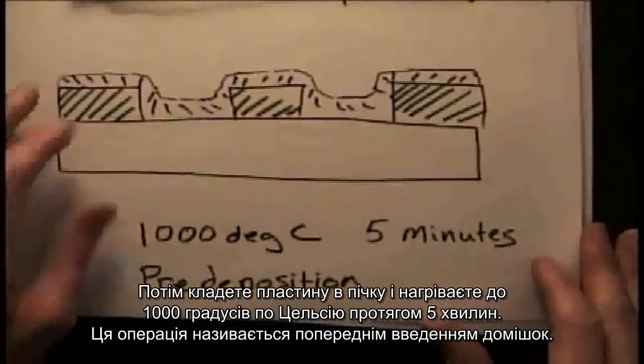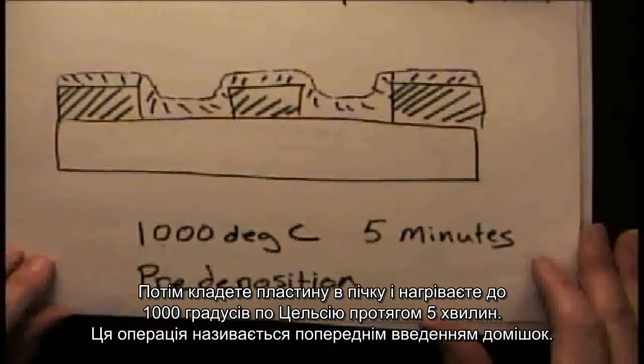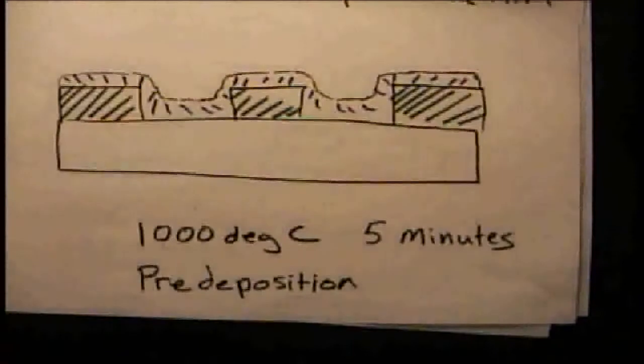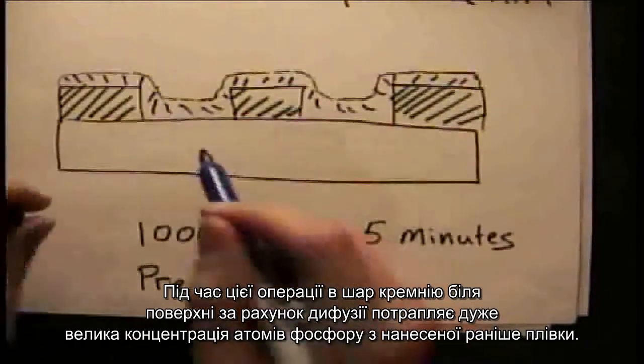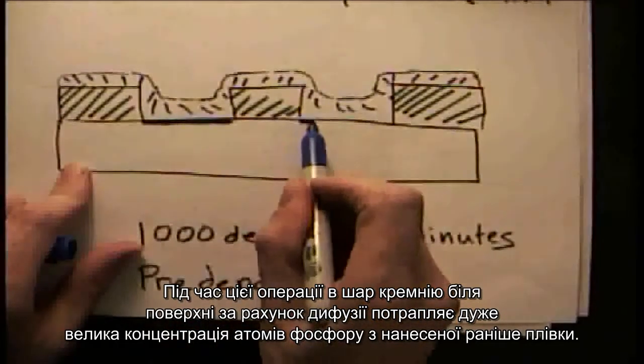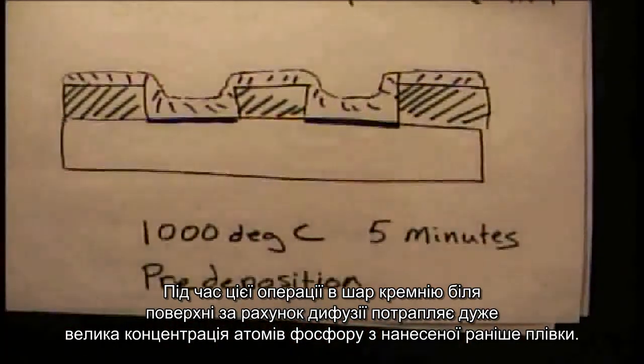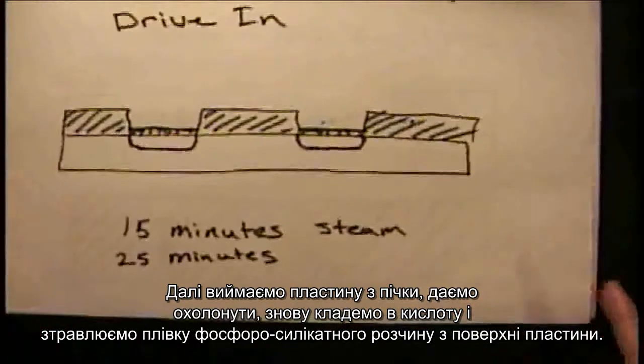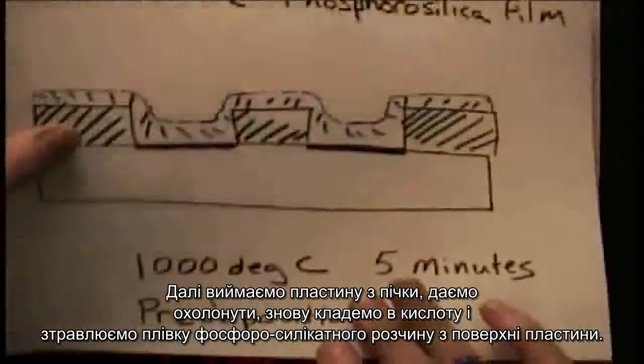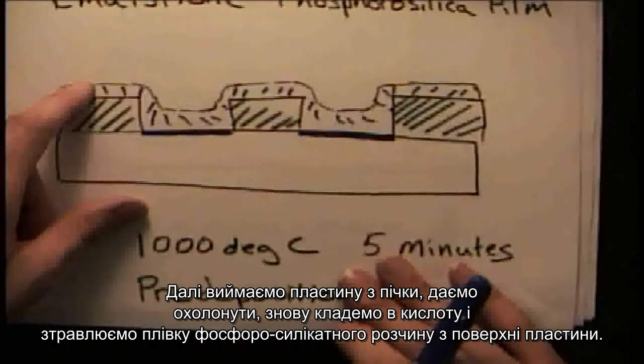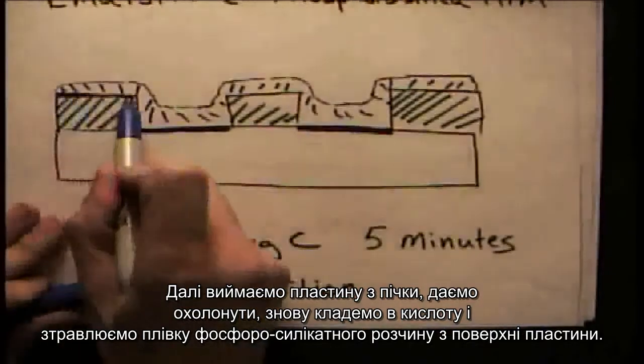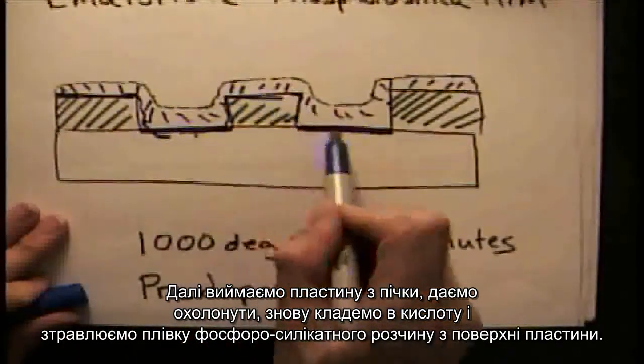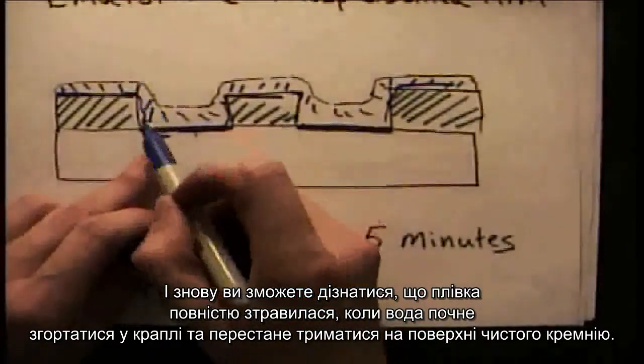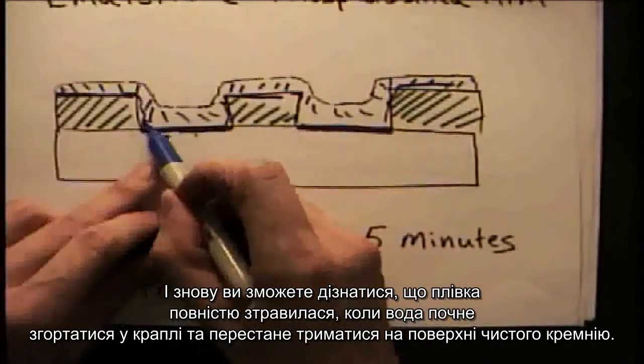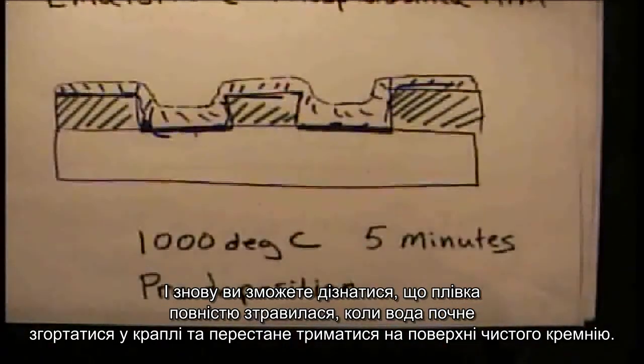Then you'll put it in your kiln at 1,000 degrees Celsius for 5 minutes for what's called a pre-deposition. The pre-deposition puts a very high concentration of phosphorus into the surface of the wafer. Then you'll take the wafer out of the furnace, let it cool down, and you'll put it back into the acid, and you'll etch away this film that was left behind. And again, you'll know that you've etched all the way through when the water starts beading up in the active areas again and doesn't wet across.